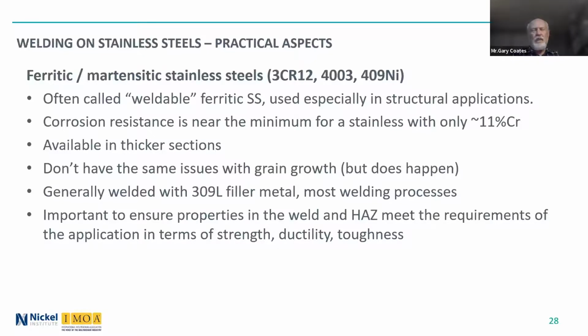You have to think ahead what properties you want in the weld and heat affected zone to ensure that you meet the requirements in terms of its strength, the ductility, and toughness. You can get these materials in strength levels that are stronger than the 309 filler metal weld properties. So then you end up with a lower strength weld, higher strength material, and that generally is not acceptable. So maybe one of you metallurgists in India will help to solve that issue, come up with a filler metal that actually is suitable for welding the higher strength versions of these alloys.